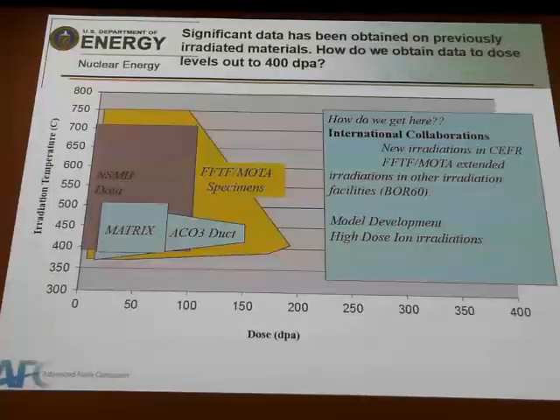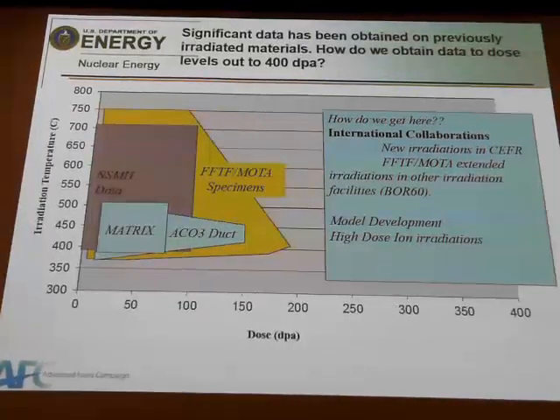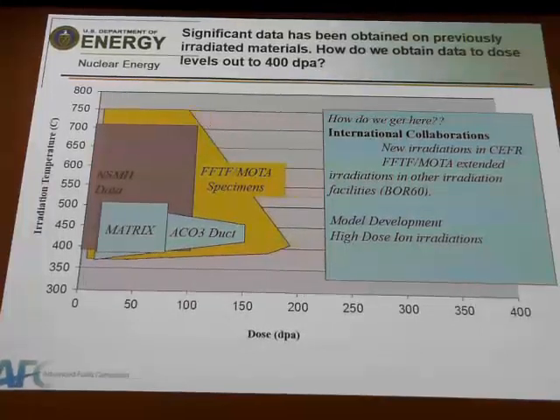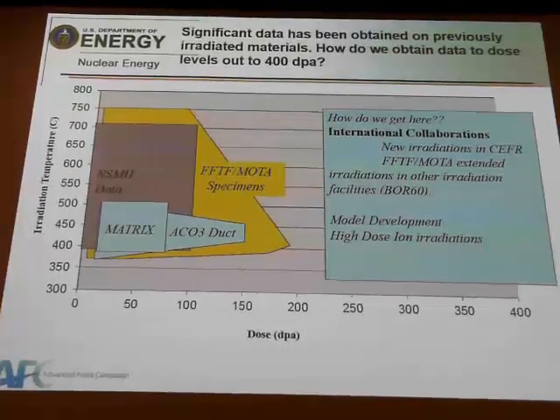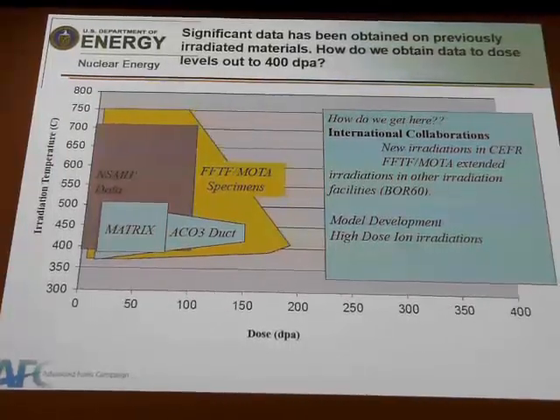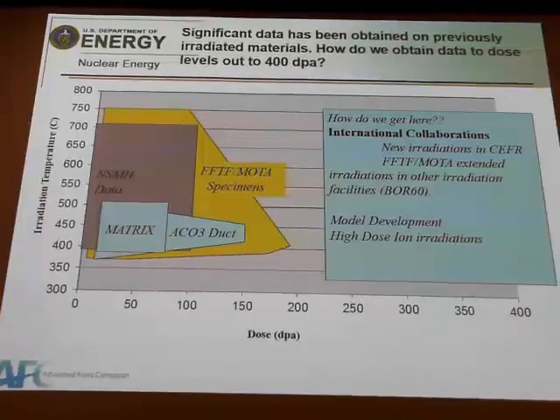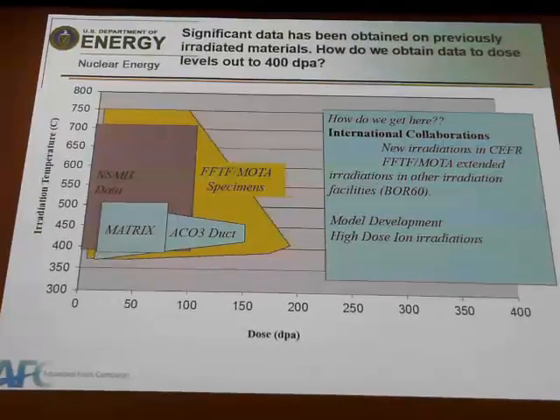So one of the other ways that we do this, and I think people here in the crowd also do this, is through high dose ion irradiations. You can get good data. You can get data to high doses, but you get it over a very small volume, and it's because of the difference in dose rate. You have differences between what you're measuring in ion irradiation and what you actually measure in reactors. So you have to translate that, or try to translate that to actual reactor data. And along with that, you need improved model development, which some of that is going on within the nuclear energy research, and I think hopefully that will continue to move forward and be improved in the future.